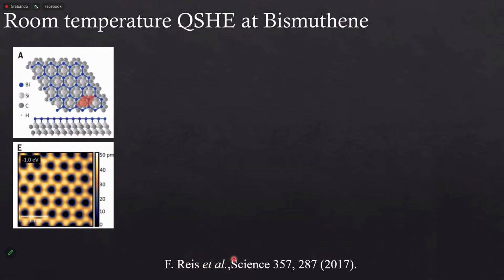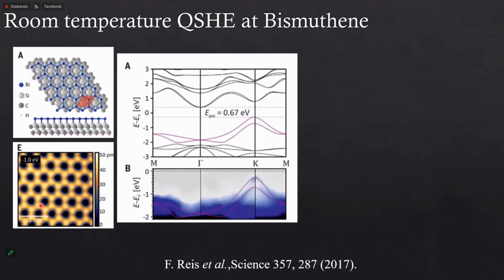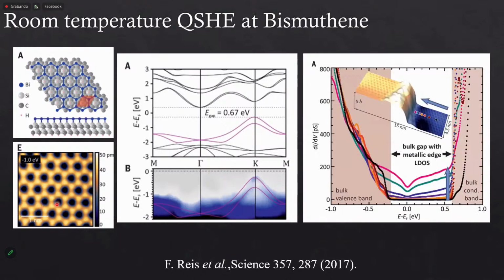So there is this very interesting Science paper from 2017, where they show that if you have just a layer of bismuth on top of silicon carbide, you form a honeycomb lattice here. And in this honeycomb lattice, you see that you have this quantum spin Hall effect. When you look at the system here, it's a bit difficult to measure this effect.